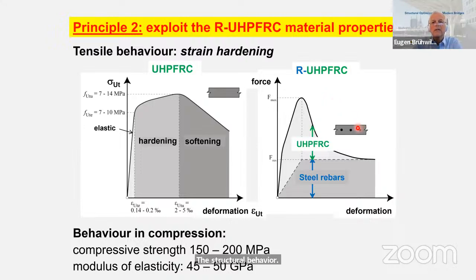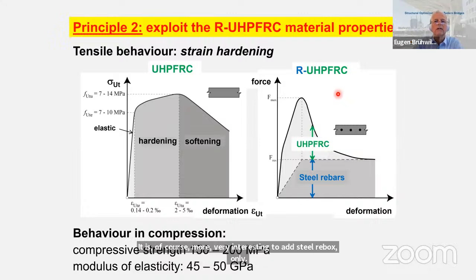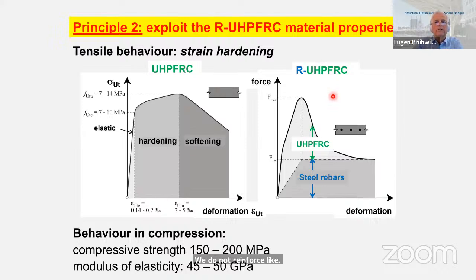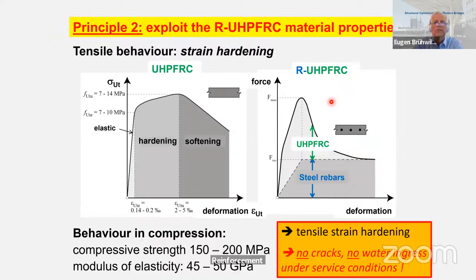And since steel rebar costs the same price per kilogram like a kilogram of UHPFRC, it is, of course, very interesting to add steel rebars, but only in the main direction. We do not reinforce like in reinforced concrete. It's different. Only in the main direction. Also, post-tensioning is, of course, reinforcement that is very interesting in the world of UHPFRC structures. So we exploit the tensile strain hardening. There are no cracks. We don't need to design for cracks or stuff like this. There is no water ingress under service conditions. Durability is very simple to be designed.